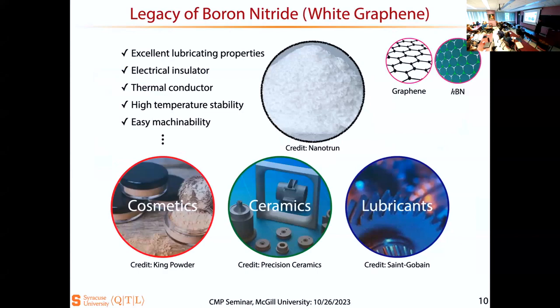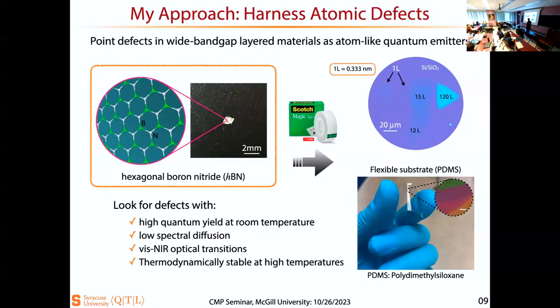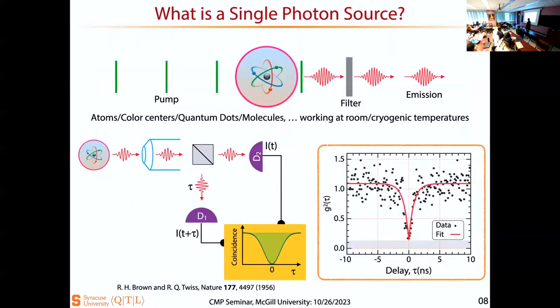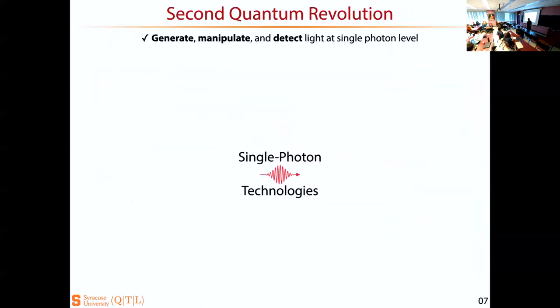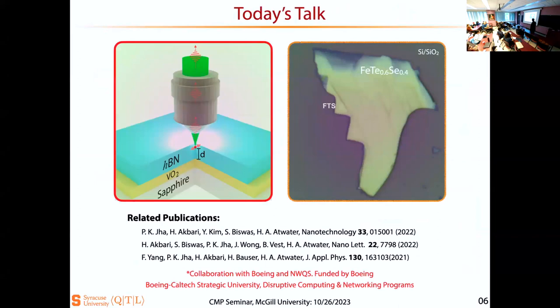So, yes. Is that the reason the CVD growth only happens on vanadium oxide? Is that the reason why the previous cartoon had sapphire, vanadium oxide, and then the hBN? Or is the CVD growth sample on top of this one? Oh, no. This one is the crystal which you bought, exfoliated, and transferred onto vanadium dioxide. Why? Oh, I'll show you why.